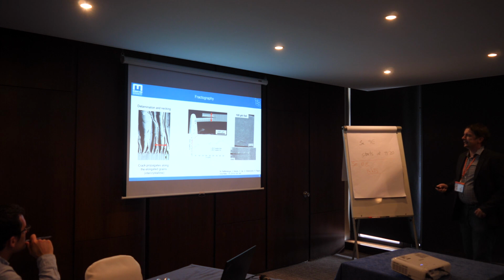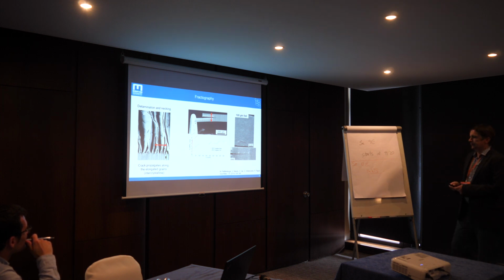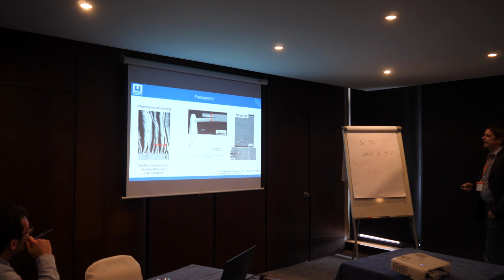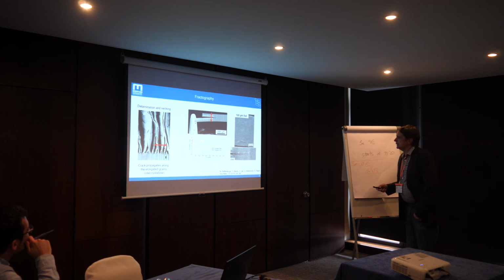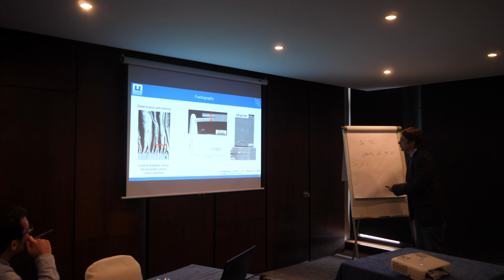We were also interested now to measure the fracture toughness in another direction. You see here, we wanted to measure the fracture toughness in this splitting direction, where we also see grain boundary fracture occurring. This we did with micromechanical experiments, and we found that the initiation toughness is only about 2.5 megapascal square root meter. Again we also had a pronounced R-curve behavior, which can be explained by the formation of shear ligaments, as you can see here probably.